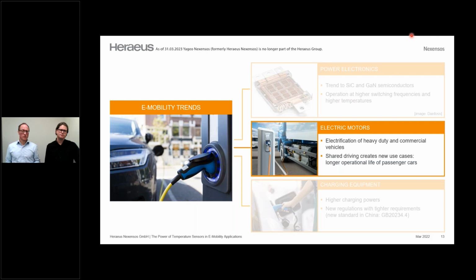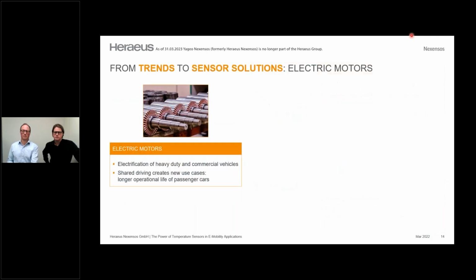In addition, we see another trend for passenger cars. Car sharing or shared driving results in longer operation times. If you compare typical operation times of a passenger car, which is in the range of 5,000 to 6,000 hours over the operational lifetime, we see much longer operational lifetimes at the moment. This impacts the stability of employed components. This creates a requirement for long-lasting components.